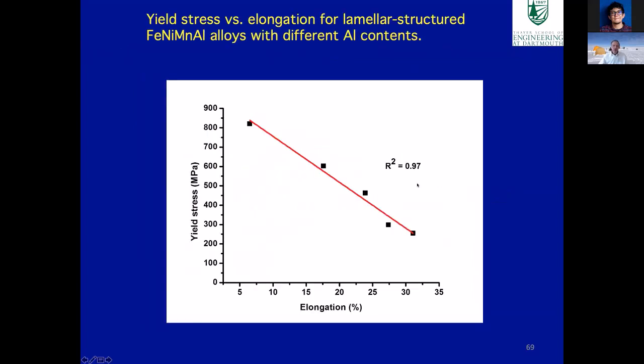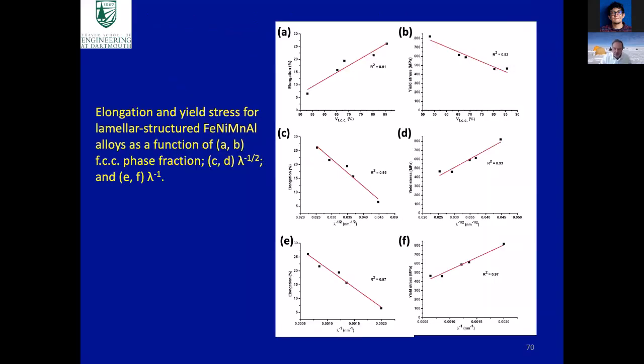So if we actually just look at the two-phase materials we've got, there's actually a very clear correlation between the yield strength and the elongation. So as you decrease the yield strength, the elongation goes up in the alloy. So there's a clear trade-off between the two. And in fact, you can plot the elongation and the yield strength as a function of volume fraction, the interlamellar spacing to the -1/2, or the interlamellar spacing to the -1. And actually, the range of values here is such that you really can't tell the difference between those two different functionalizations very well.